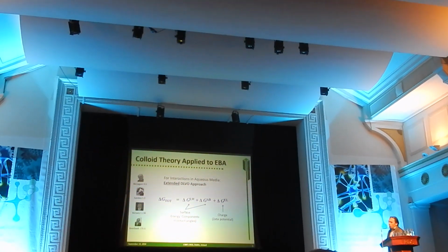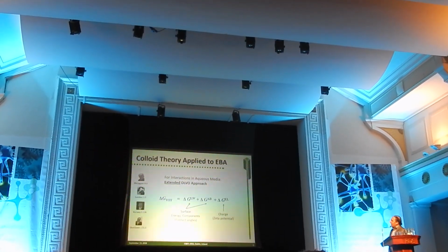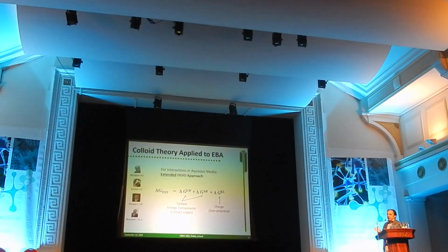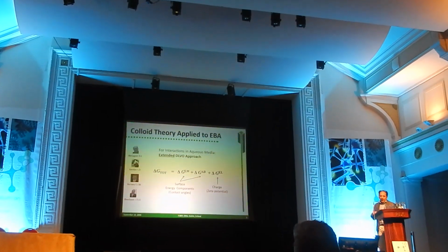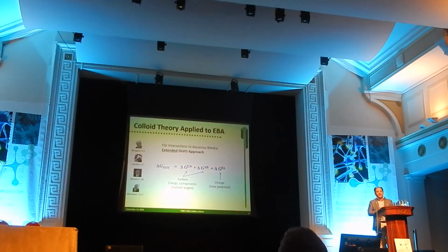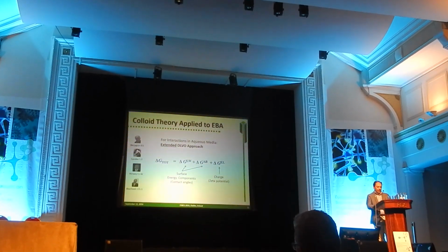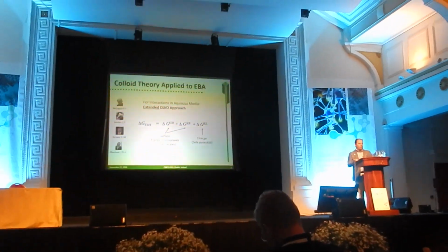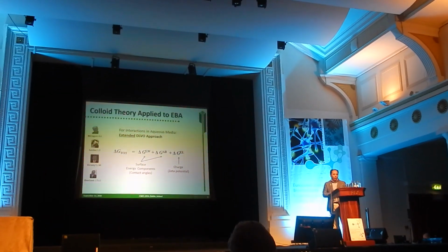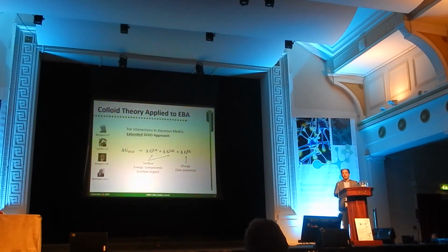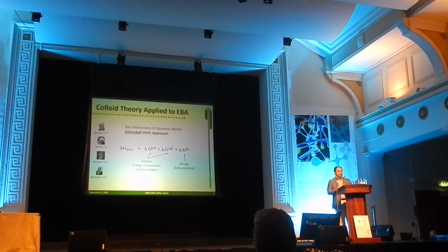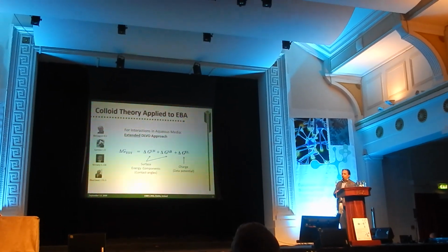So we are looking now at free energies of interaction between surfaces, or particles in our case, right? And we are taking a specific theoretical framework, so not the standard DLVO technique that was basically made in vacuum by physicists, but the extended DLVO approach, which is made for particles making contact or interacting in aqueous media, which is, of course, the bioprocessing situation, right?